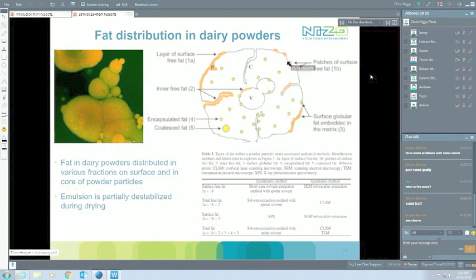And if we draw it schematically, we can find some of our initial emulsion droplets on the surface, and we can live with that. They can be there if they need to be, but it's these big patches of free fat, of surface fat that we want to avoid, and that's about controlling our emulsion stability, and that's where, of course, our initial processing, particularly our homogenization, is very important, but also what happens during atomization, because you can actually undo all the good work that you did in your homogenizer in advance by putting too much on it during the atomization again afterwards.